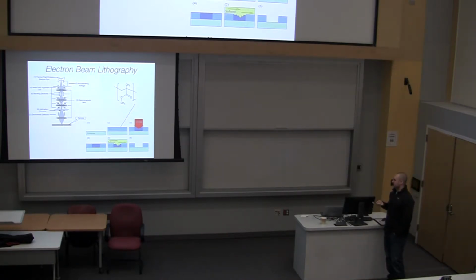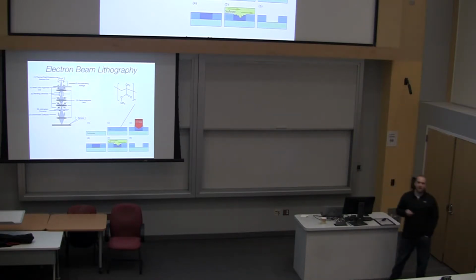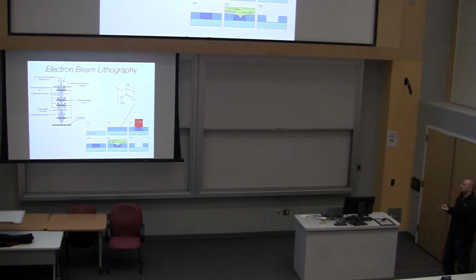The sample has something on top of it. The typical something that you put on top of it is something called polymethyl methacrylate, which is a polymer chain of these, whatever that is, I have no idea, some chemistry thing. But the important thing is that when chains of these molecules see the e-beam, they start to break apart. So let's say this is my film, I've shown the e-beam right here. Where the blue is darker, these chains have been sliced apart into their individual constituents.